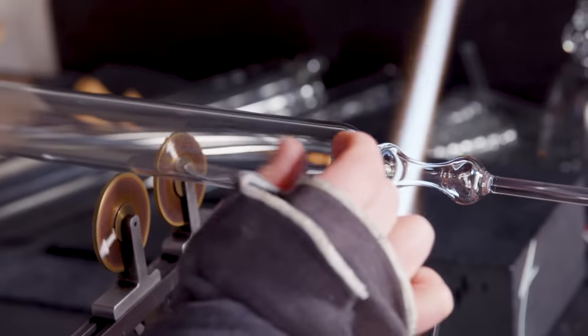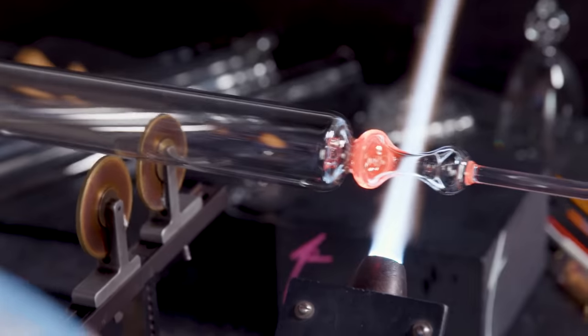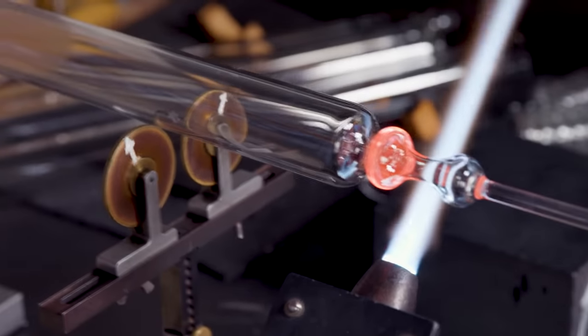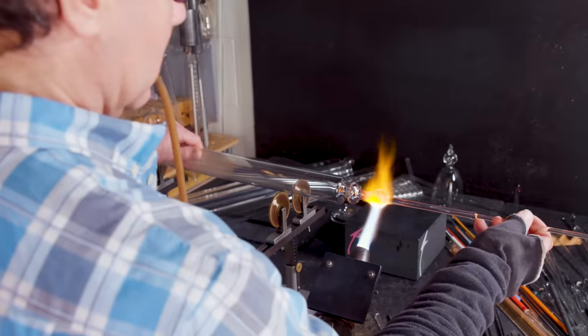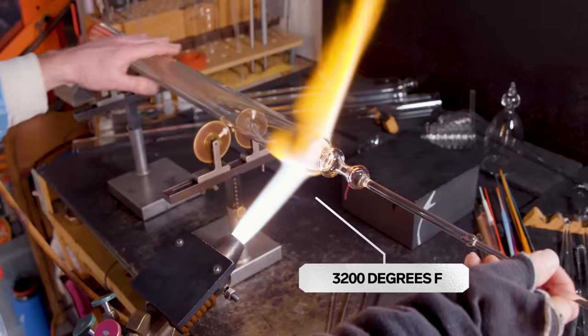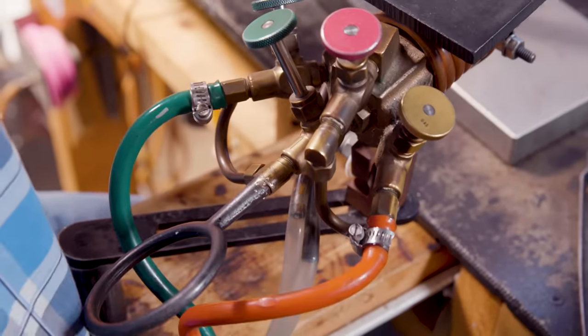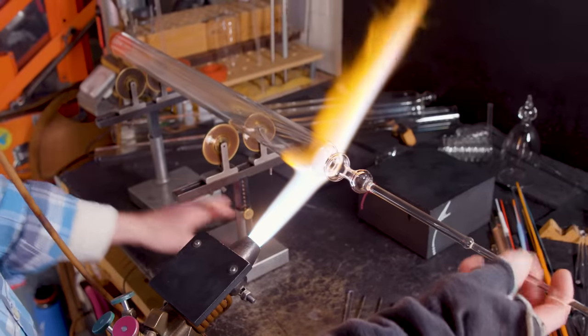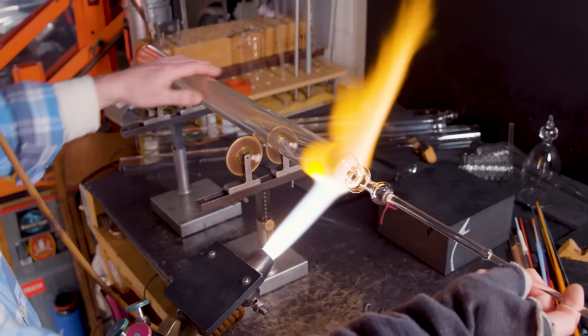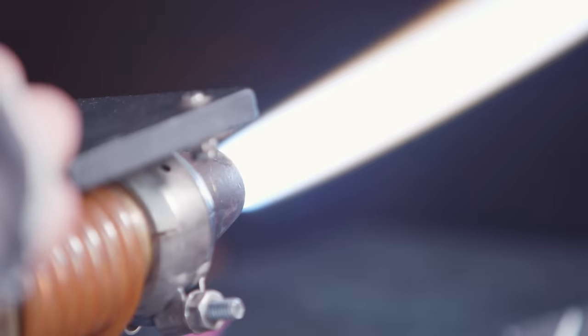Now I'm going to blow this up and squash it a little. I use quite a bit of heat, 3,200 degrees Fahrenheit is the actual flame temperature. The valves on the torch are the control for propane and oxygen to give different flame intensities and flame patterns. There's the focused, wide, soft flame. Like when I blow a cup, I use the outer fire to get more glass soft so I can blow a bigger bubble.